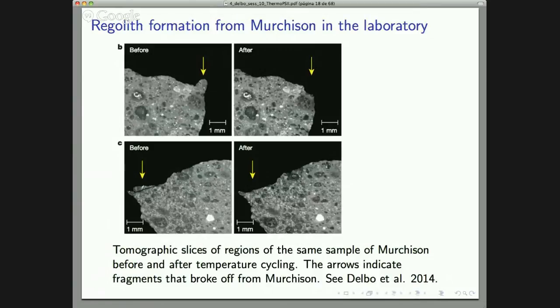We took great care to make sure that we didn't cause this by handling the meteorites. We did another experiment with more or less the same setup, but we didn't activate the thermal cycling in the oven. We left everything at the same temperature, and we saw no crack growth nor production of debris.